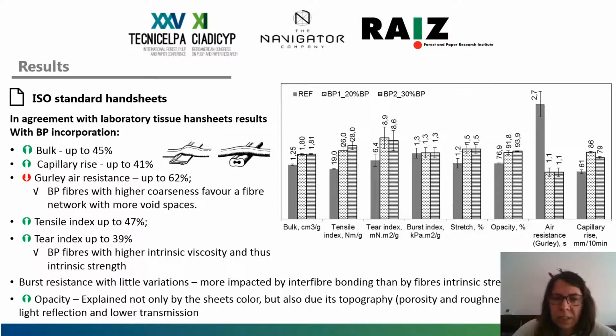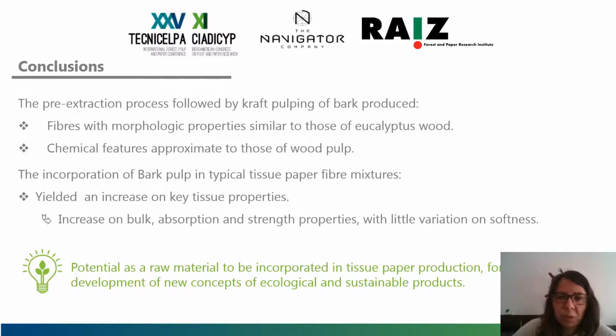As regards opacity, the incorporation of bark pulp resulted in a sheet with higher opacity, also with some slightly creamed color. In conclusion of this work, we found that the pre-extraction process and kraft pulping of bark resulted in fibers with similarities in case of biometric properties to those of eucalyptus wood, and also similarities between chemical properties of bark pulp